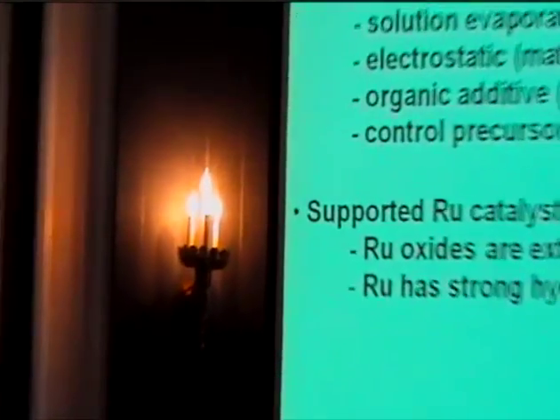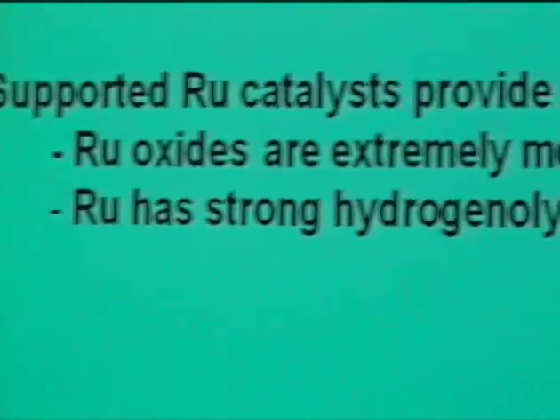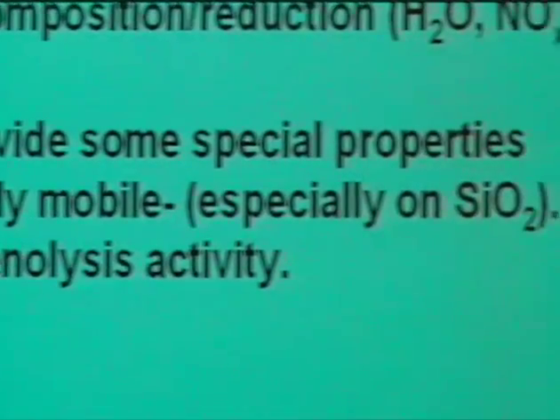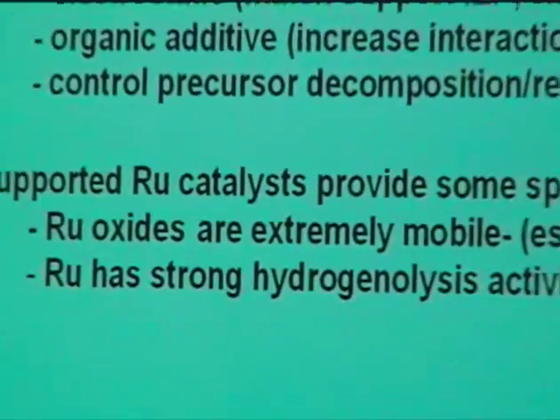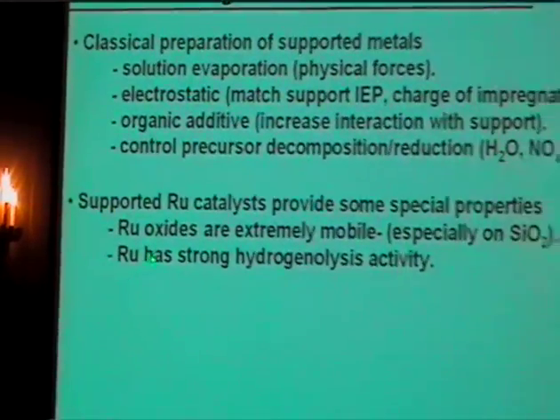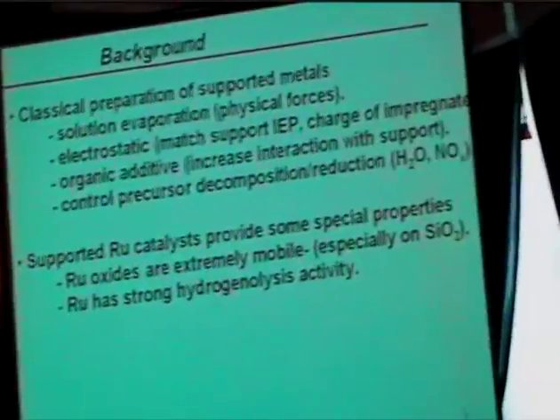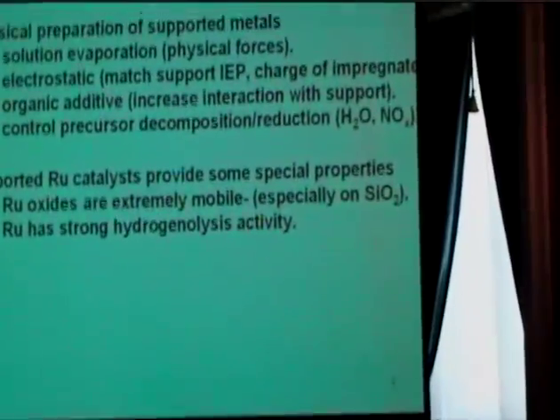Other issues that are important: sometimes the actual decomposition of the precursor turns out to be important, particularly if you have gas evolution of NOx, water, and so on. That can have a lot of influence on the way that the metal winds up because of mobility issues. Now, ruthenium has some special properties. And what are those? Well, ruthenium oxides can be extremely mobile, especially on silica surfaces. And we were going to be working on silica here, trying to work with essentially a neutral support. Okay, the other issue with ruthenium that actually turns out to be an advantage is that it has a very strong hydrogenolysis activity. We're going to take advantage of both of those.